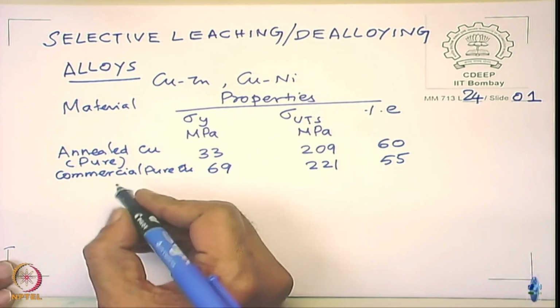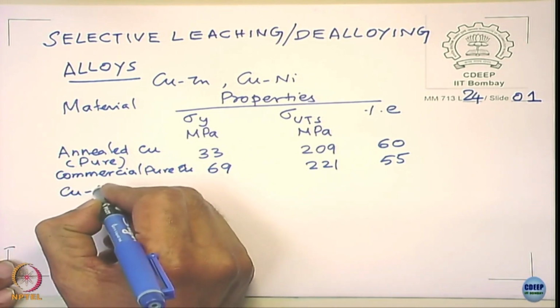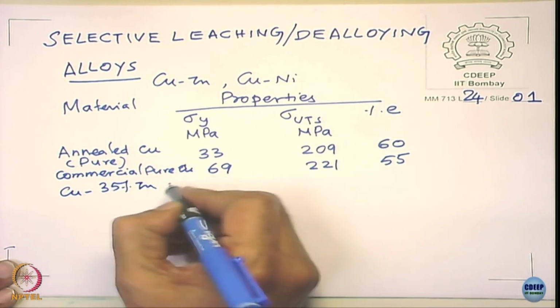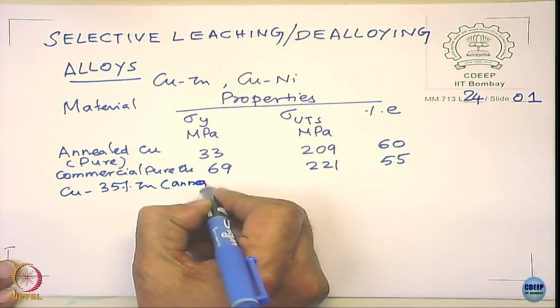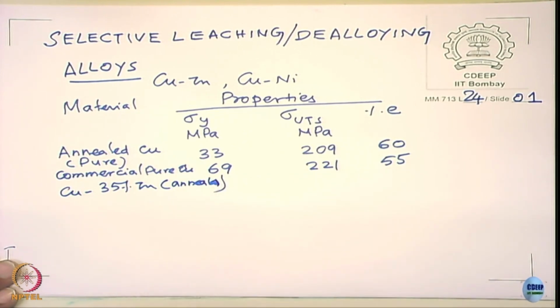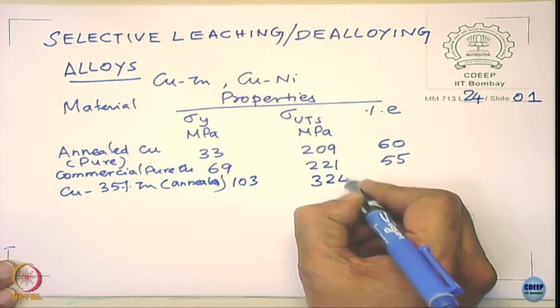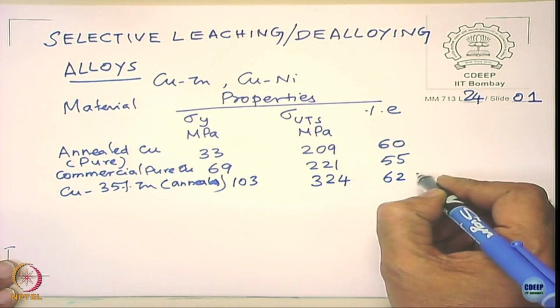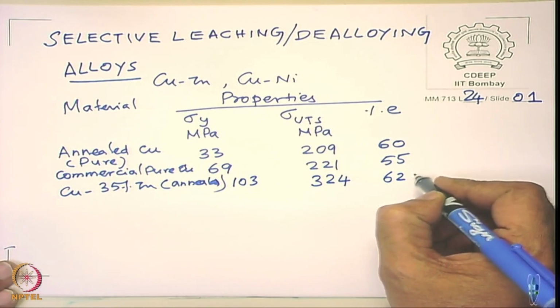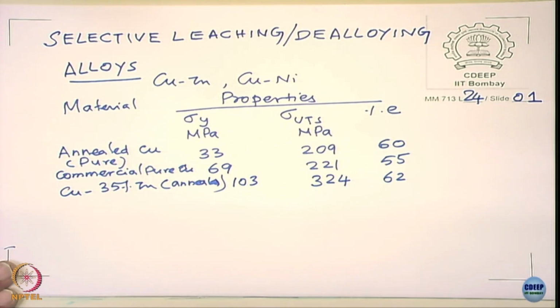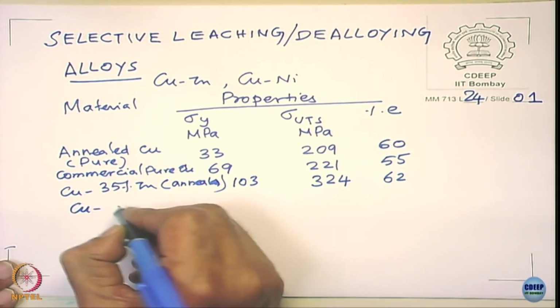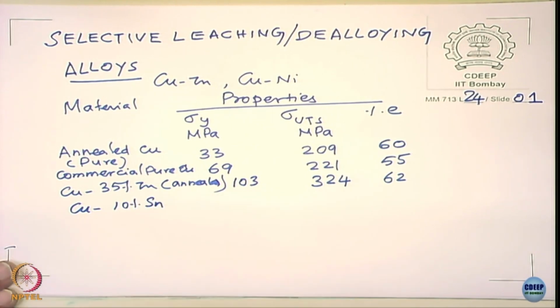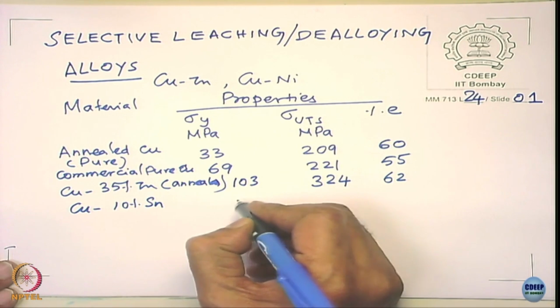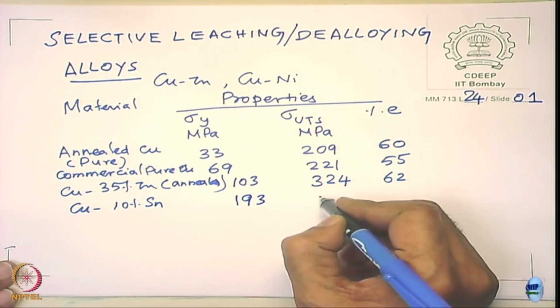But if you take a brass, which is copper 35% zinc, which is annealed, you will see the strength increases quite significantly. In this case, even the elongation is improving. If you take, let us say, copper 10% tin, you can see that the strength level is again increasing.